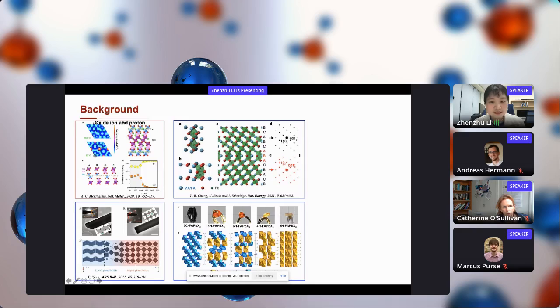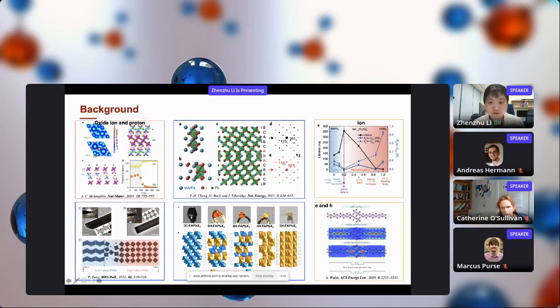The existence of the stacking faults in such polytypes will modify their carrier behaviors. For example, in this material, the lifetime of carriers was dramatically decreased due to the existence of the 2H interlayer phase. And also in our previous work, we found the hole block and the electron trap in this 3C8H CsPbI3 polytype.